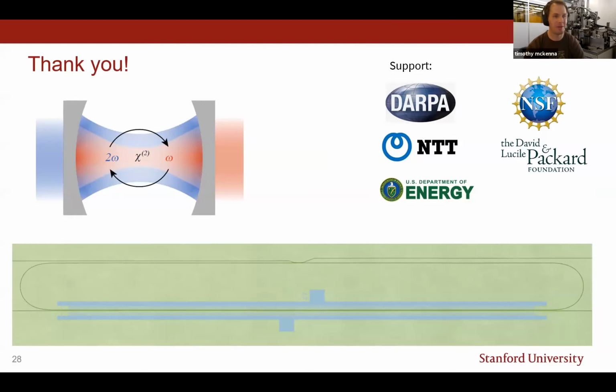Oh, sure. There's a lot of things that go into this. There's actually a couple different types of disorder, but basically when we make these resonators on the surface of a chip, it's probably not as clean as a crystal in between two mirrors. Instead, different modes will sample some of the imperfections of the fabrication differently. That's one thing. So we normally see our intrinsic Qs vary by like 1%.